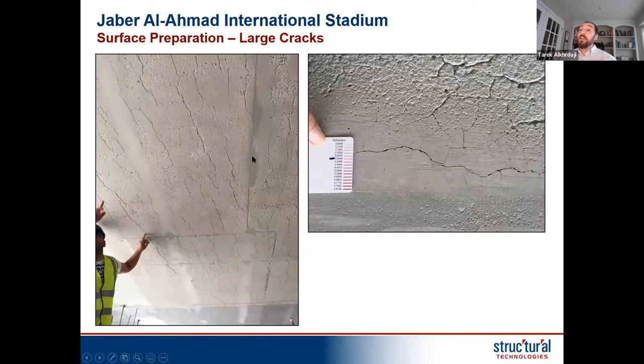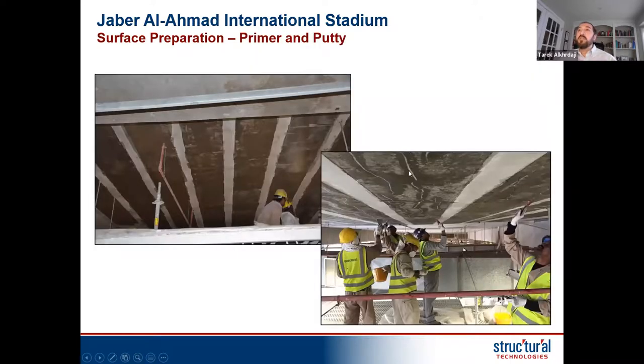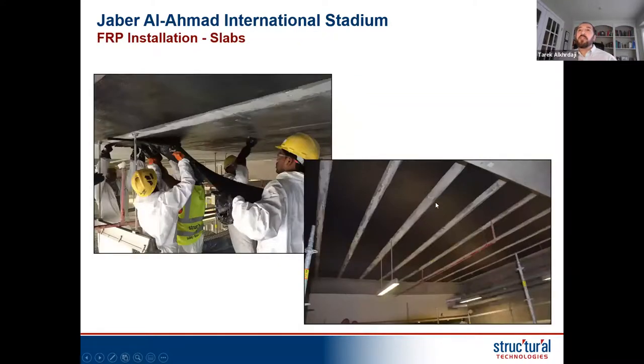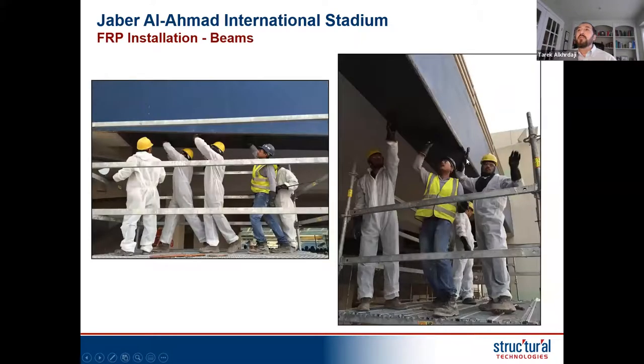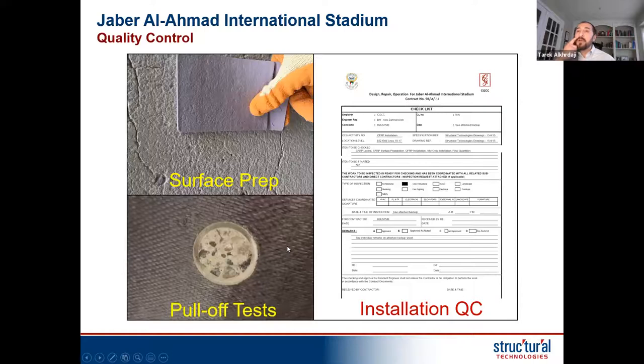And this is what I wanted to show you. You remember I mentioned earlier that the concrete may look good, but once you grind it or remove the outer layer, you can see all the micro cracks. All of these things did not show before you removed the concrete. So now you have to really prep this, prime it, and fill everything with thick epoxy to help glue it together and fill all these voids. You can see it in here. Everything is filled. Big ones are targeted with epoxy. And then after that, you bring in saturated fabric and install it on the underside of the slab. Here you can see the fabric on the bottom. And then after that, apply the U-wrap to the concrete.